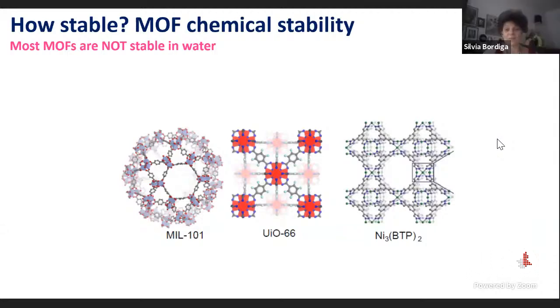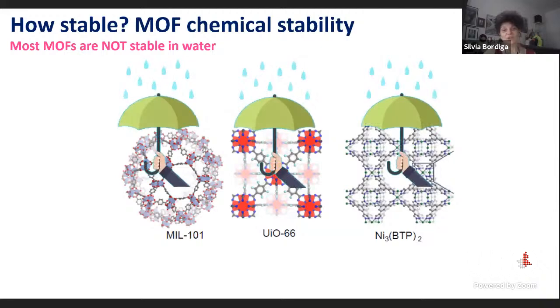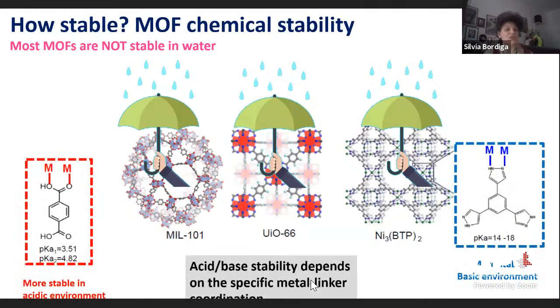As I told you, the removal of the solvent is important, and sometimes after the solvent removal, what we obtain is a material with a large porosity, but then we have to be careful about the stability of the material. In fact, most of these materials are not stable in the presence of moisture, and they are destroyed, so they lose crystallinity when they are in contact with water or just the moisture of the atmosphere. So some of them cannot find broad application because of this problem. For instance, UiO66, if it is made in a proper way, is able to resist also the contact with moisture, but this is not always the case.